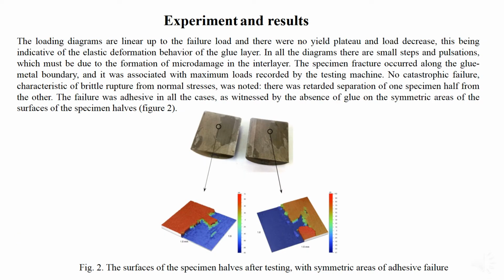The loading diagrams are linear up to the failure load, and there was no yield plateau or load decrease, this being indicative of the elastic deformation behavior of the glue layer. In all the diagrams there were small steps and pulsation, which must be due to the formation of micro damage in the interlayer.